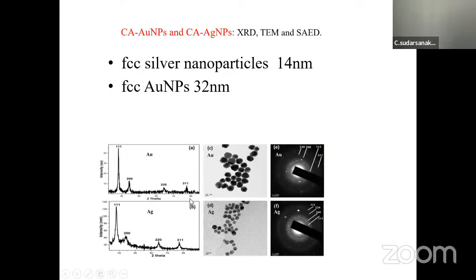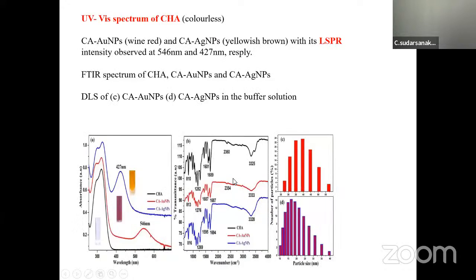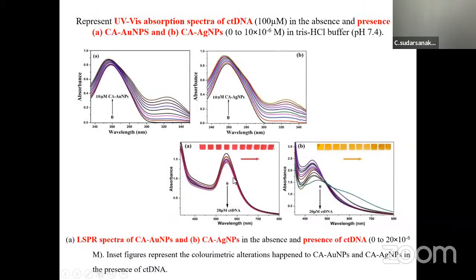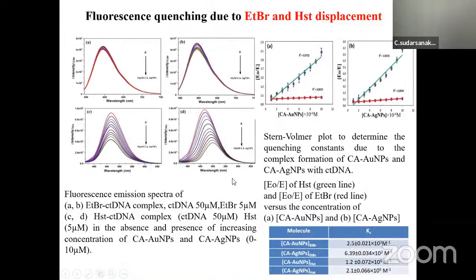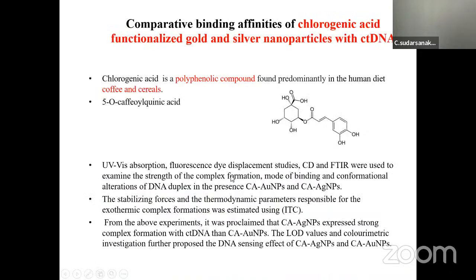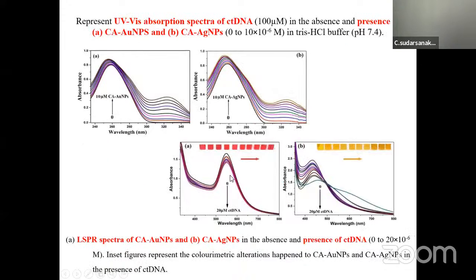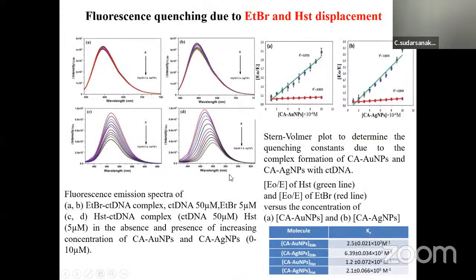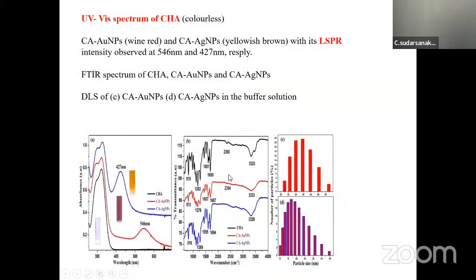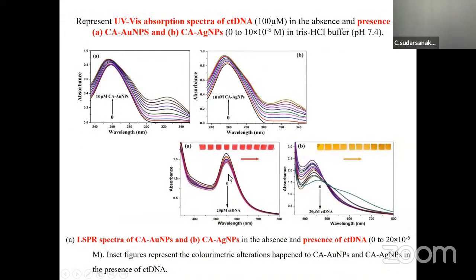Now, the complex with the gold and silver nanoparticles. You don't find very many changes in the XRD pattern, but you find some kind of agglomeration. Okay, I don't have that slide. Fine. When it's a complex, we have all these analyses, but some kind of agglomeration is observed because of the surface functionality. Then you find the UV-visible absorption.